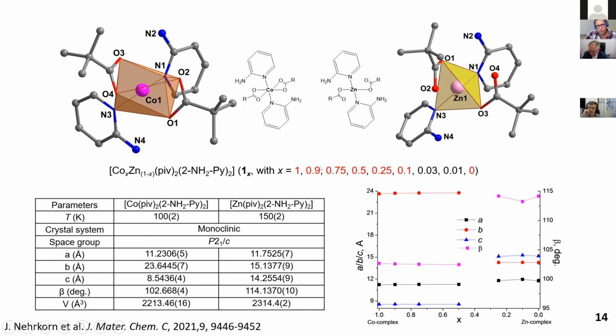We synthesized different compounds with different ratios of metal ions. The red numbers show that crystals were analyzed by single crystal X-ray analysis. We analyzed the metal ratio and phase purity. First we see the breaking point where we have the transition from cobalt-rich to zinc-rich samples. It is about 50% of cobalt and 50% of zinc. Cell parameters don't change significantly in both series, as you can see.